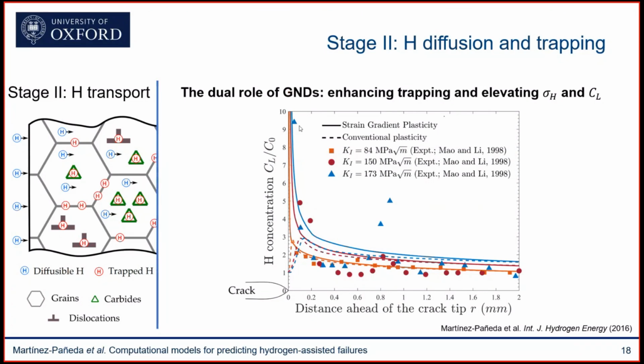And there's a lot of experimental evidence showing very high hydrogen concentrations near crack tips. And again, only through these GND effects can you explain this. And as I show later, this is also important because I would say that this is the only way to rationalize the decohesion mechanisms.